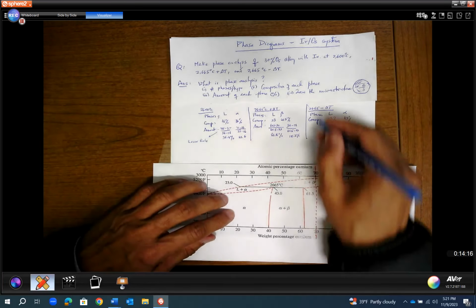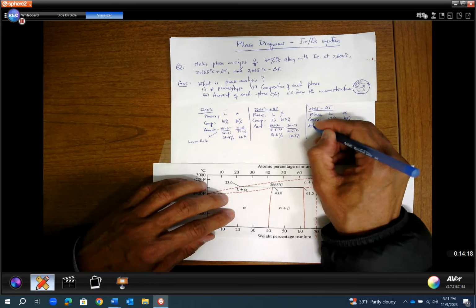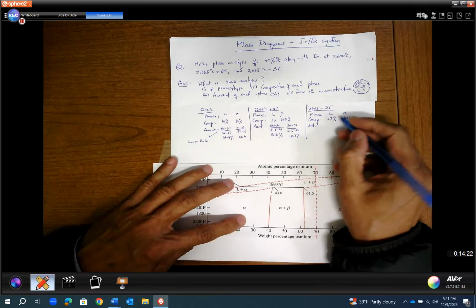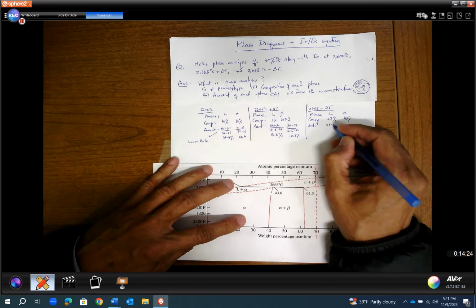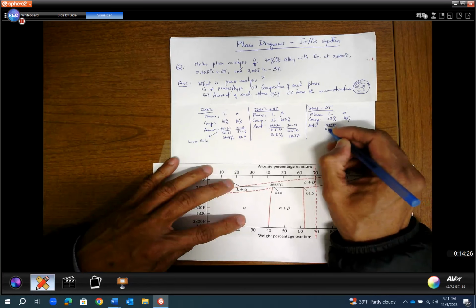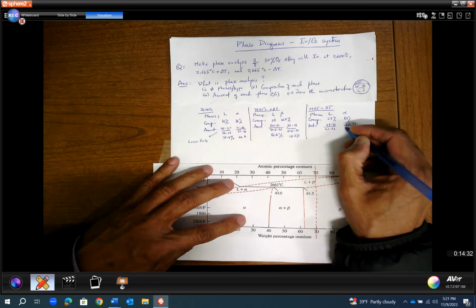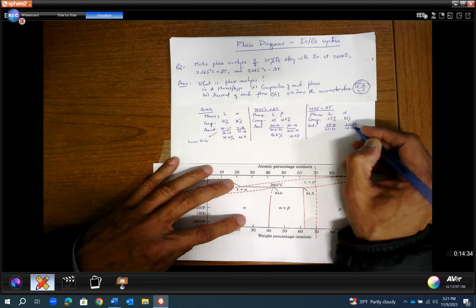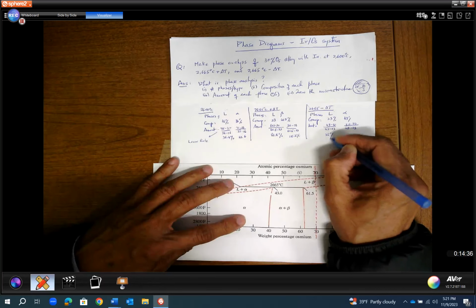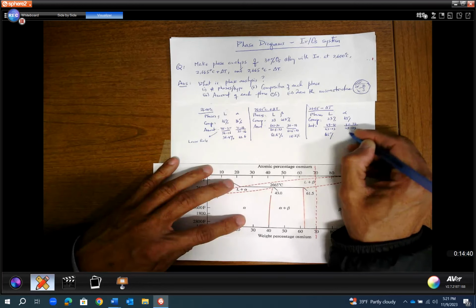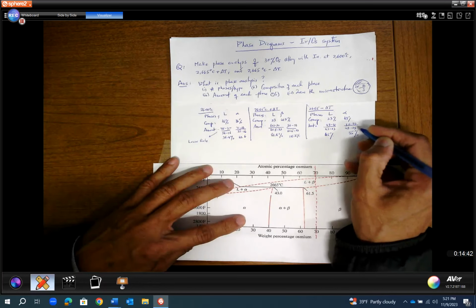And then, of course, the amount becomes pretty academic in that the liquid side is 43 minus 30 divided by 43 minus 23. And then for the solid, it is 30 minus 23 divided by 43 minus 23. That's 35%, so, 65% liquid, 35% solid.